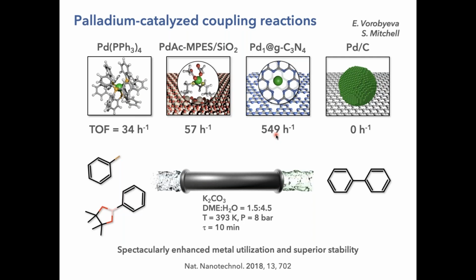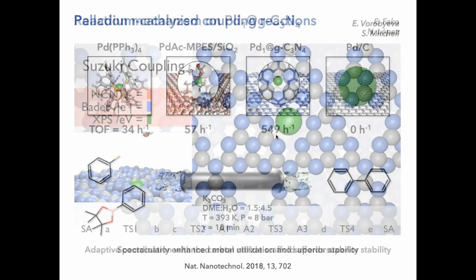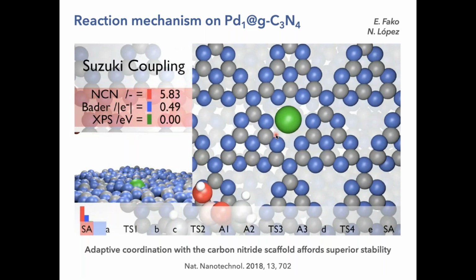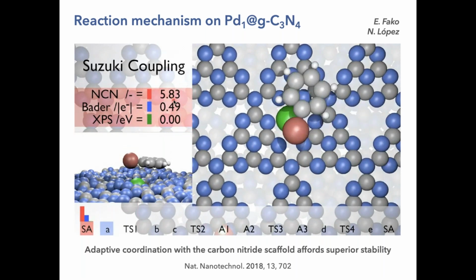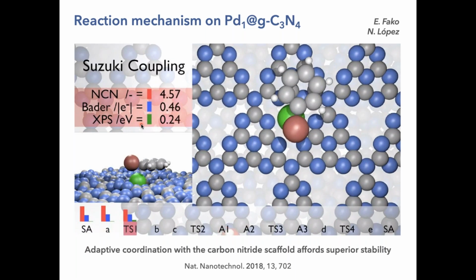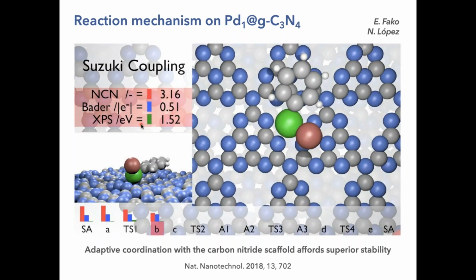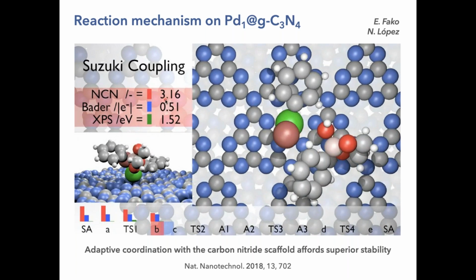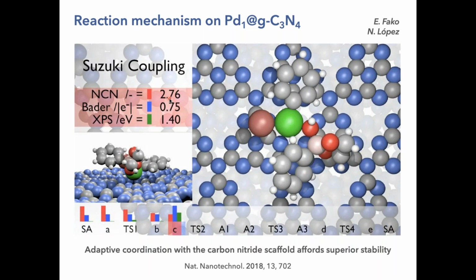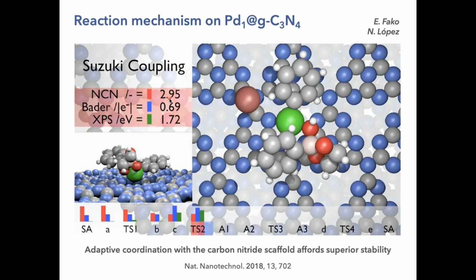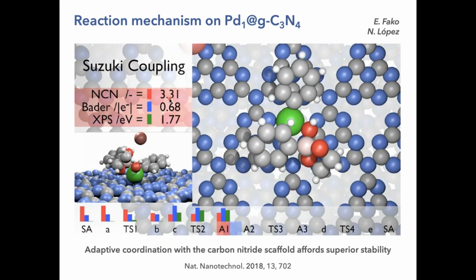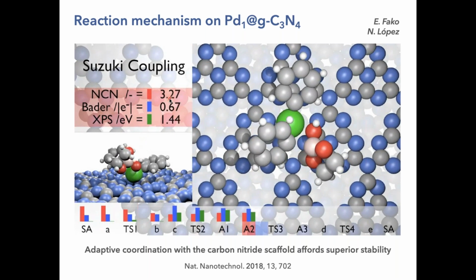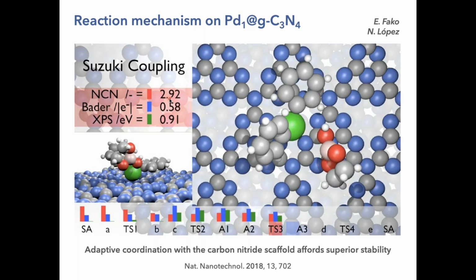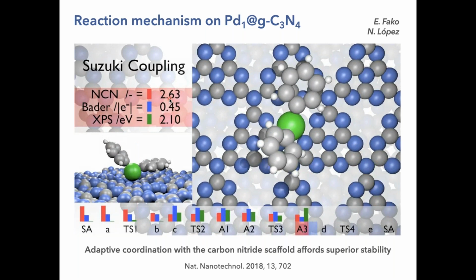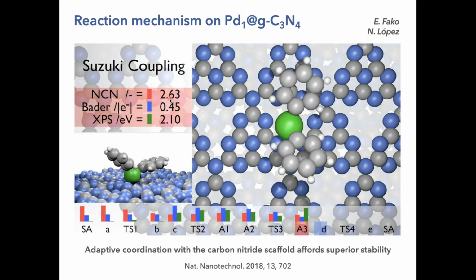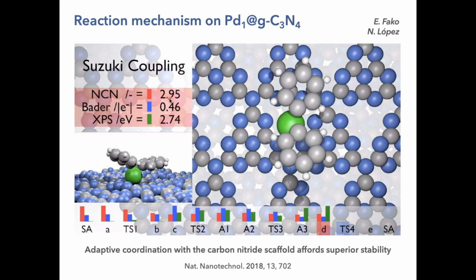To explain the high activity and stability of this system towards leaching or towards agglomeration, I think this picture will enable us some clarity. This is the coordination of the atom to the host, right? So it's surrounded by about 6 nitrogens. When there is the adsorption of the bromobenzene, of course, the single atom loses some coordination to the host because it's coordinating the reactant. So it decreases to 2.76, as you see over here. The reaction proceeds, and the beauty of this system is that the single atom can adapt its coordination in this cavity. So it's actually locked enough not to leach, but is flexible enough to adapt its coordination optimally to the adsorption of reactants or intermediates, leading to a decreased energy transition and therefore a very high activity.